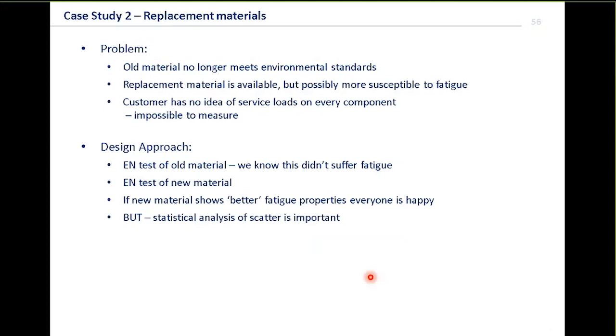So our approach here is we do an S-N test of the old material. We know this didn't suffer at all from fatigue. We'll do a test of the new material. And if that new material is better than the old one, everybody's happy. The problem is, very often, it's not quite as clear cut. So in this particular problem, our customer didn't know the service loads of every component that they'd manufactured. It wasn't possible to measure it. So again, we had to use statistics.